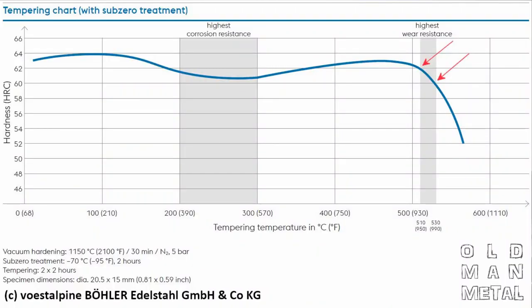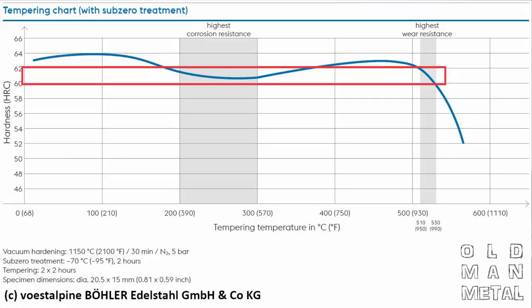And optimal wear resistance, if that's what you're going for, that actually requires a third tempering step at an even higher temperature. And it's worth noting that the final hardness starts dropping off really rapidly at the tempering range for optimal wear resistance. So if you're tweaking it for wear resistance, you've got to be careful because your hardness is going to start to drop off on the far side of that. And Benchmade specifies their M390 as having a finished hardness of between 60 and 62 Rockwell. That could be either scenario or one in between.